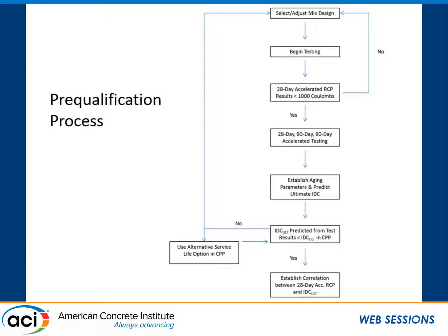Now, sometimes the concrete itself doesn't have to be the solution for the durability. Sometimes you add other systems. You might have the reinforcing, instead of black steel, you might want to use a galvanized or an epoxy coating or a stainless steel. Then you might add surface treatments. You might have coatings. You might have other things that you can apply. So the concrete itself doesn't have to meet it, but the whole package together does.